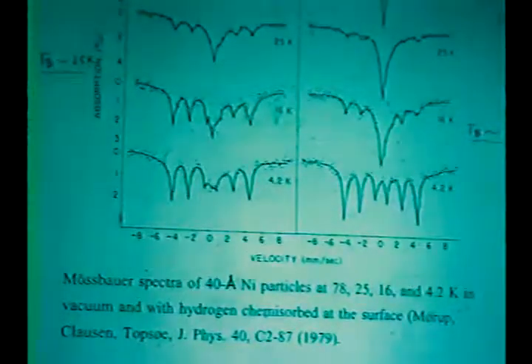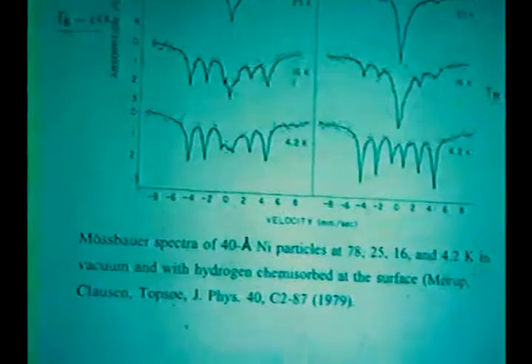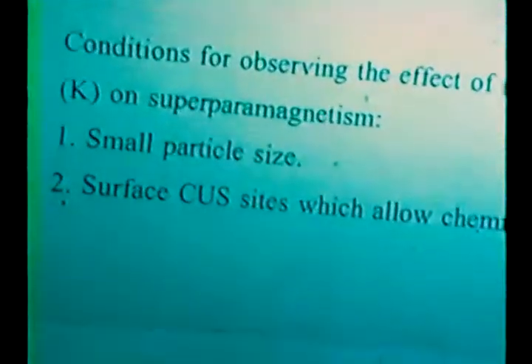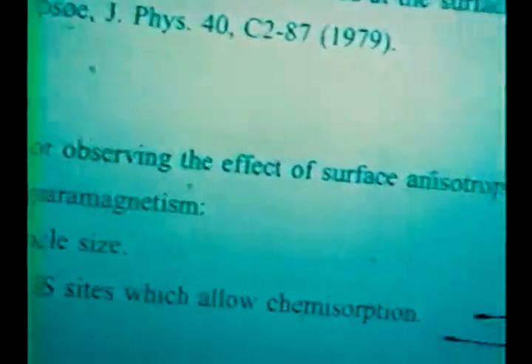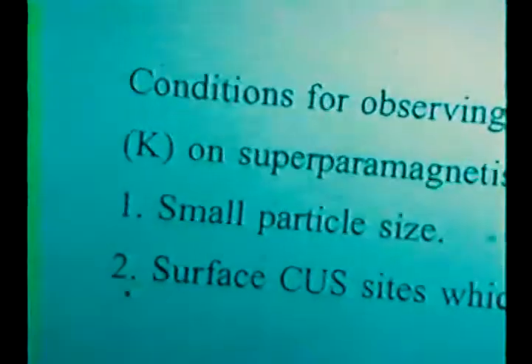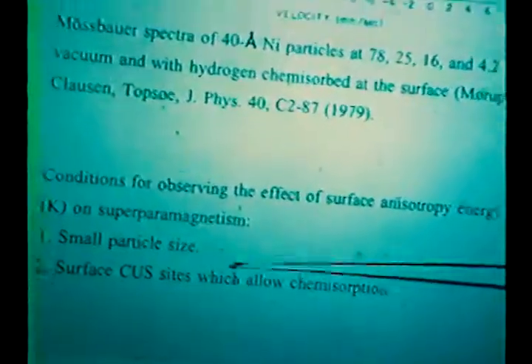In order to see the effect of surface, this is purely due to surface adsorption. So in order to see the effect of surface anisotropic energy on superparamagnetism, two conditions have to be satisfied. First, we have to have a very small particle size, because small particle size gives a larger fraction of surface. Second, the surface has to allow chemisorption.